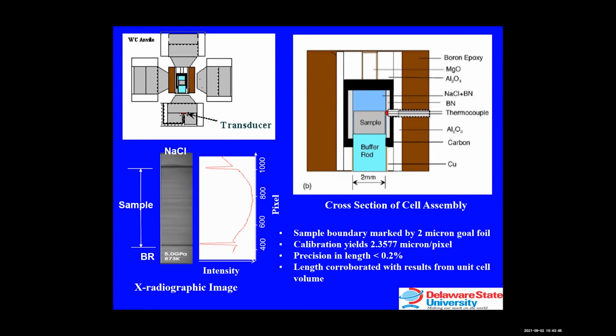So accurate temperature measurement is achieved in this cell by direct contact of the tungsten rhenium thermocouple on the sample, as shown here. And in some experiments, to create symmetry, we have mounted two thermocouples, and we can read the temperatures. The temperatures match within 2 to 3 degrees centigrade. We also insert a 2-micron gold foil at the top of the sample and at the bottom for imaging the sample length. The precision for direct measurement of the sample length using this technique, that's using the image, is about 0.2 to 0.4%.